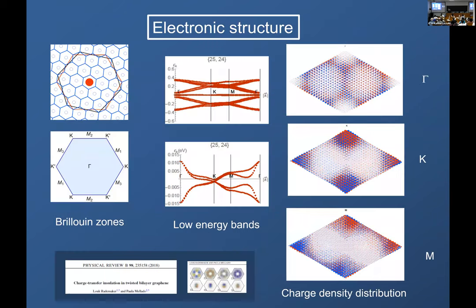So at the end of the day, these wave functions have a lot of internal structure. And this is an interesting issue that was pointed out. The point is not very clear in this paper. You have flat bands, and typically flat bands in a narrow band system are associated to highly localized atomic orbitals, let's say f orbitals in uranium or something like that. That is not the case. They look the same no matter where in the band you are. That's not the case in twisted bilayer graphene. It happens that there is a big difference whether you are at the gamma point or at the K point of the mini Brillouin zone.